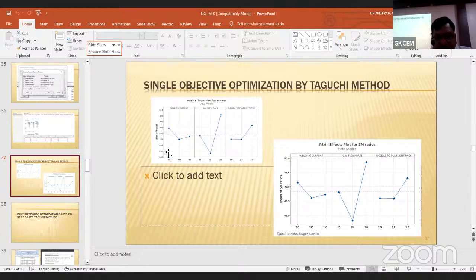So at 90 amps, this position is higher, so this point represents the higher value. This point gives a value of 20 gas liters per minute, and 3.0 millimeter is the nozzle to plate distance. This gives us an optimal solution of the particular problem. The problem is to weld stainless steel of thickness 3 millimeter.